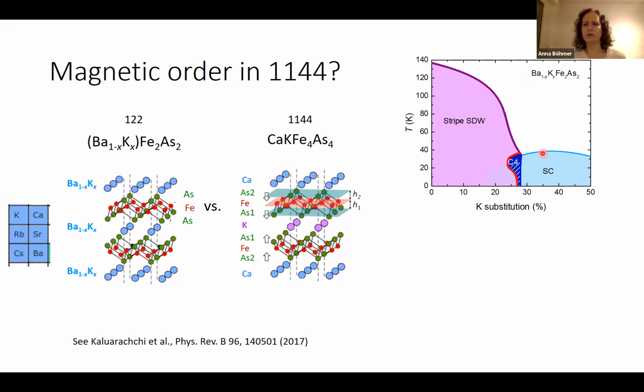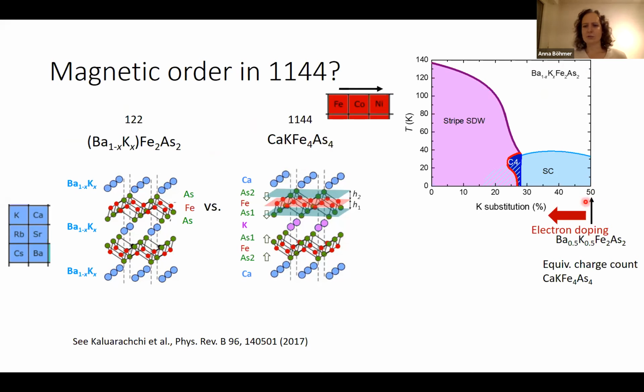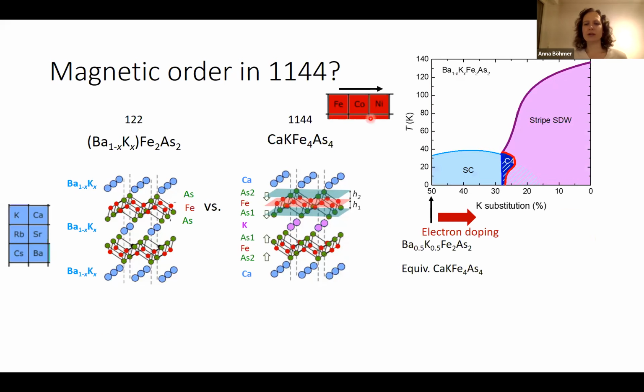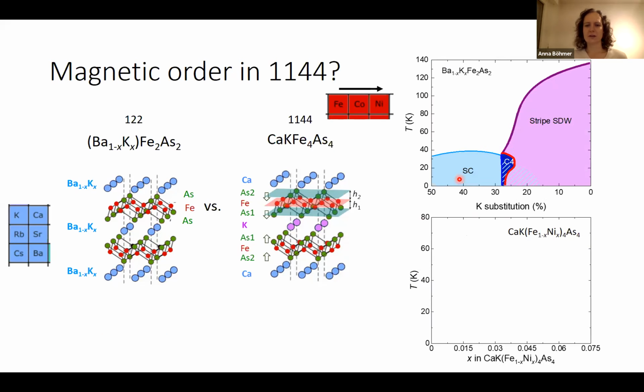And we are here on the right-hand side. By charge count, we are equivalent to the 50-50. If we want to go towards magnetic order, now we need to reverse, we need to electron dope. And we can achieve that by substituting with, say, cobalt or nickel for the iron. So to do that, let me just plot this inverse and put the phase diagram. And what I will talk about today is the nickel substituted calcium, potassium, iron 4, arsenic 4.